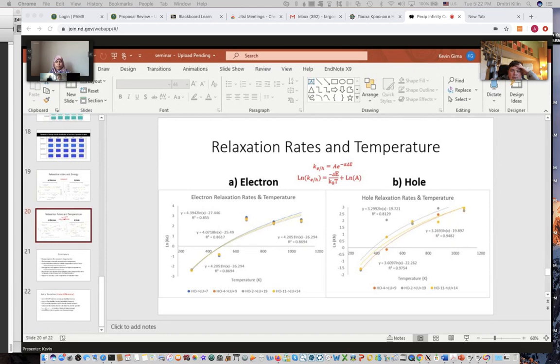Okay, here are my relaxation rates, and here we're studying how they increase with temperature. So in panels A and B, we can essentially see that the graphs overlap each other. They're on top of each other. And what that means is that the rate of change for the relaxation rates with respect to temperature is independent of the orbital transition. So no matter what orbital transition you're studying, the rate of change for that relaxation rate with respect to the temperature is going to be the same for all of the transitions.